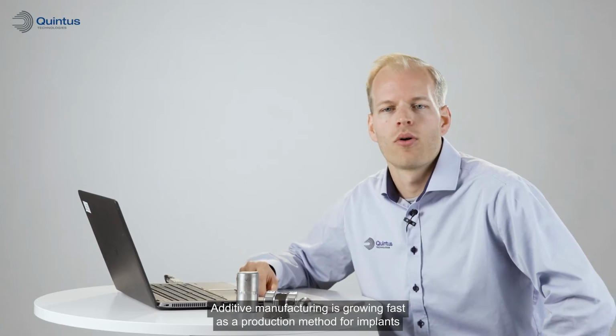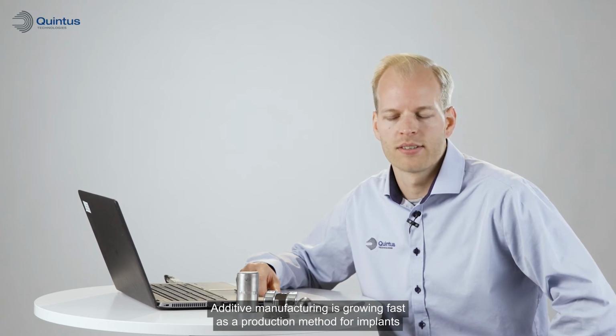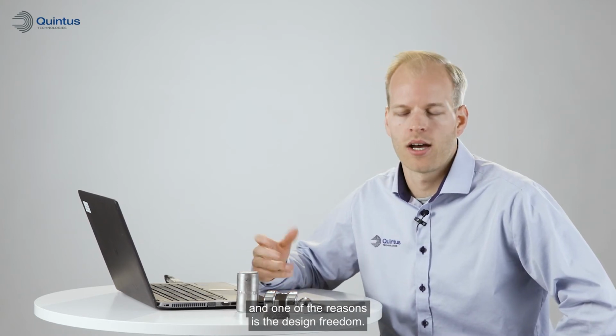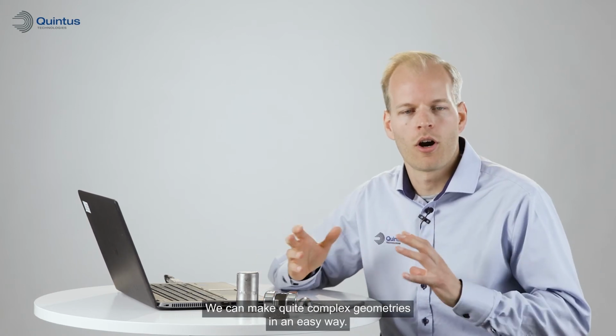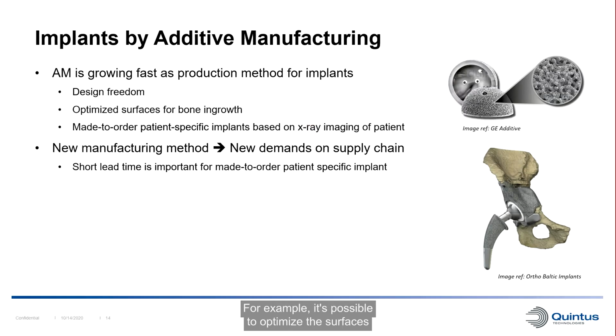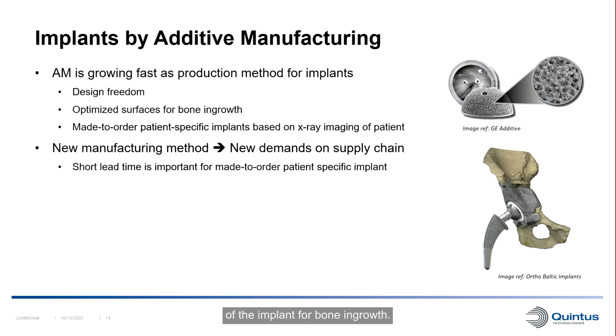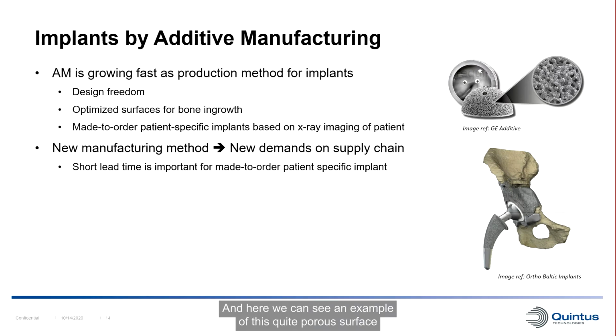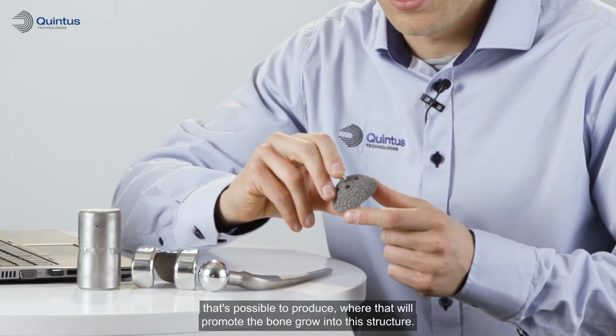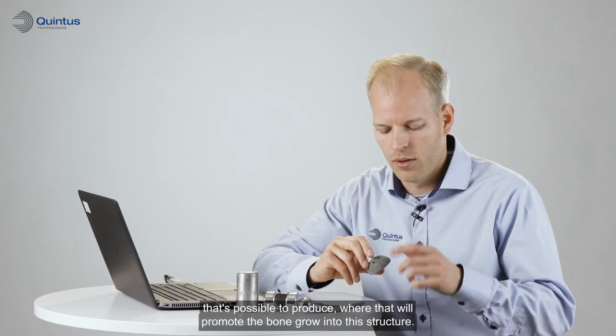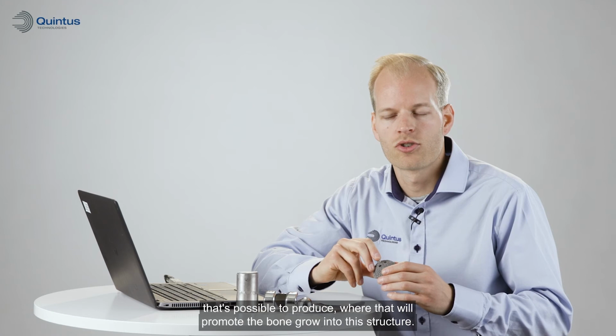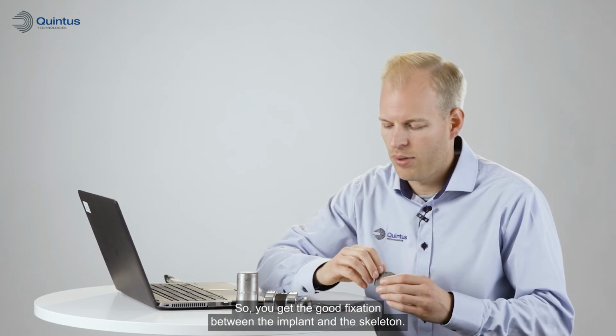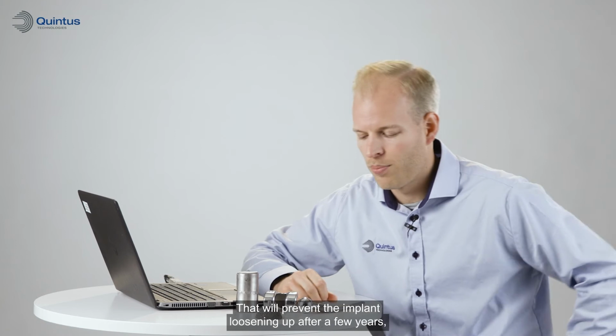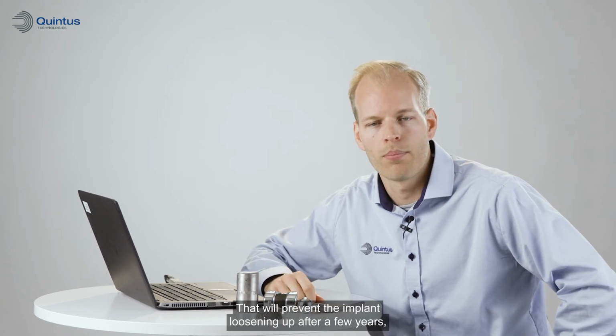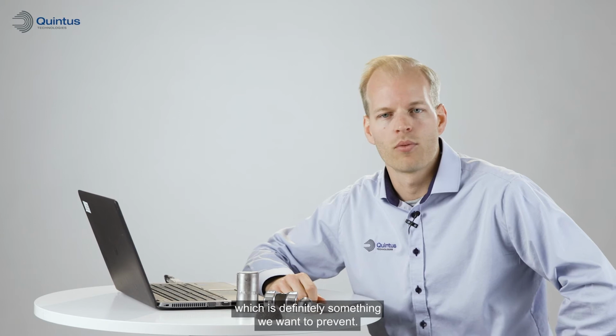Additive manufacturing is growing fast as a production method for implants, and one of the reasons is the design freedom. We can make quite complex geometries in an easy way. For example, it's possible to optimize the surfaces of the implant for bone ingrowth. And here we can see an example of this quite porous surface that's possible to produce, where that will promote the bone to grow into this structure, so you get a good fixation between the implant and the skeleton. That will prevent the implant loosening up after a few years, which is definitely something we want to prevent.